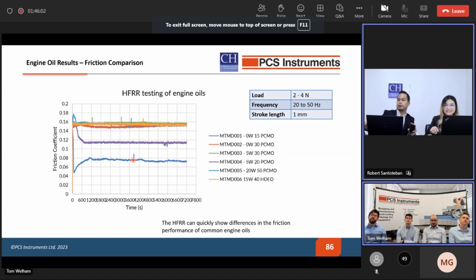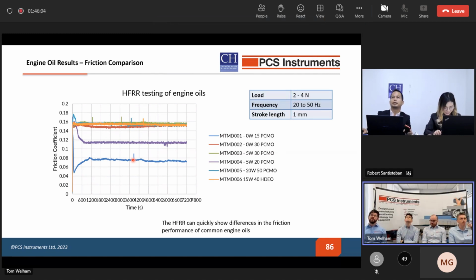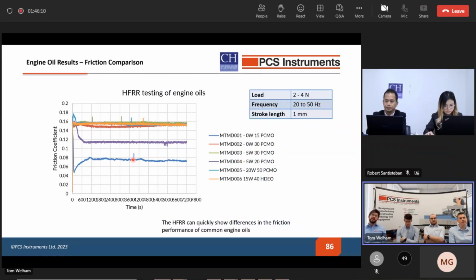And we can see that the typical testing parameters of these tests where you're looking at friction and comparing oils would be about 2 to 4 newtons of load, and a frequency of 20 to 50 hertz, and a 1 millimeter stroke length. And we can see that there is a significant difference between all the oils, so this would be very useful for a lubricant manufacturer who's looking at developing oil formulations and wants to see the level of friction and wear happening on their tests.